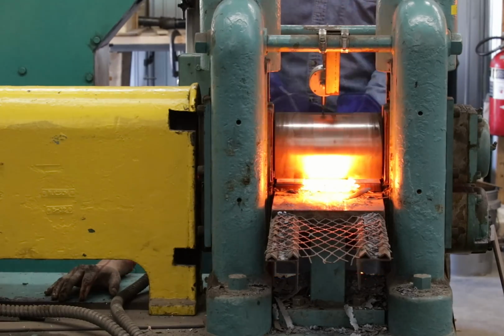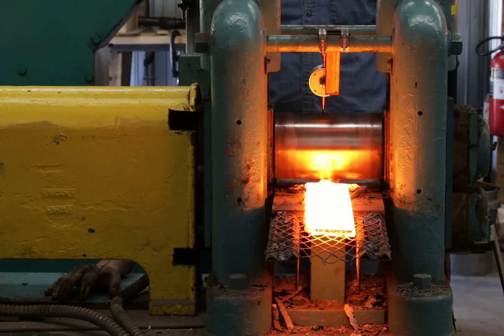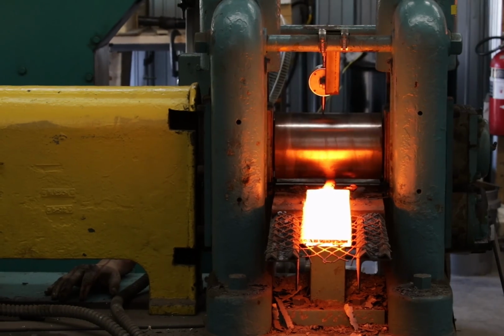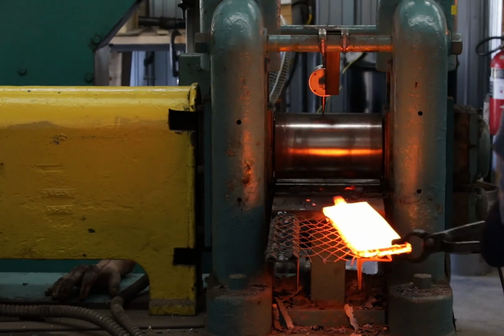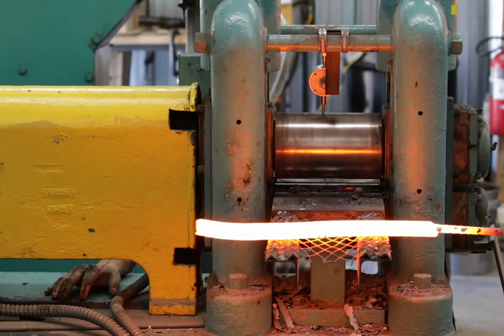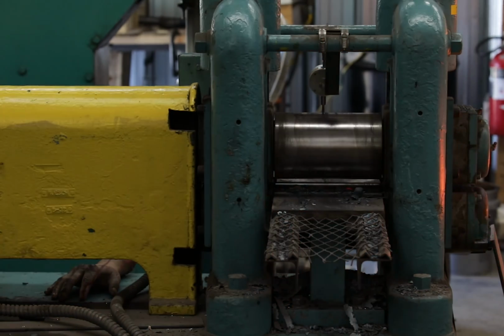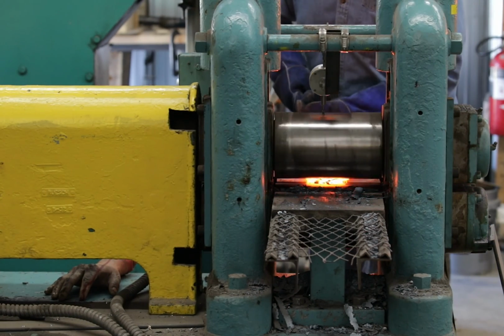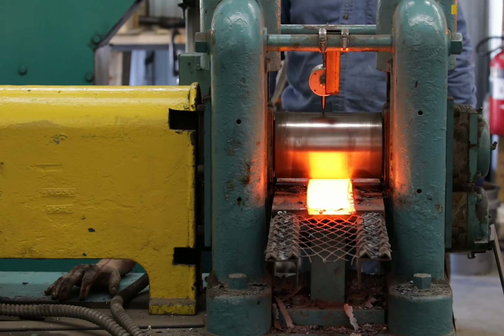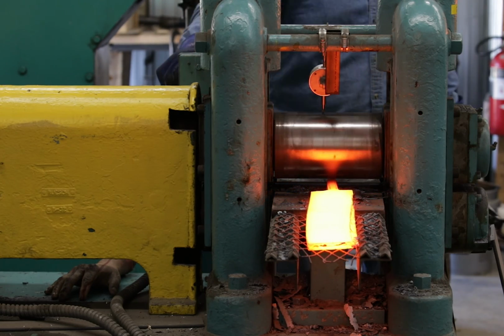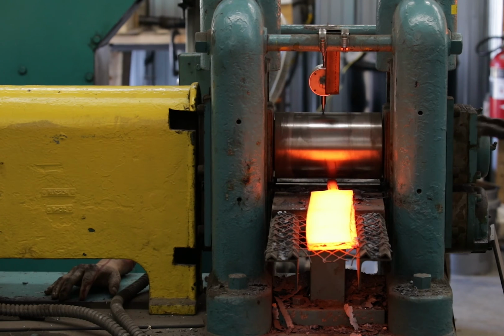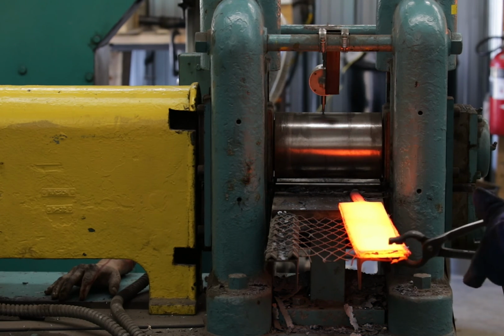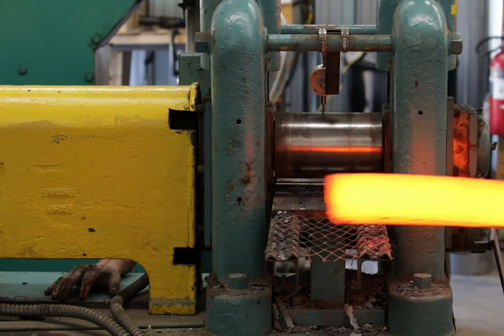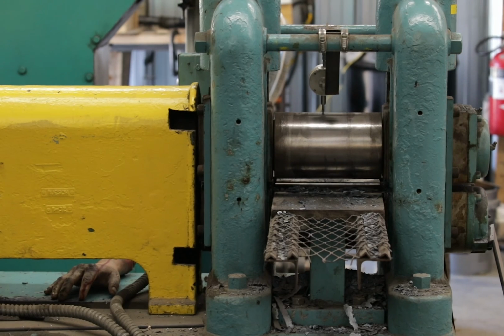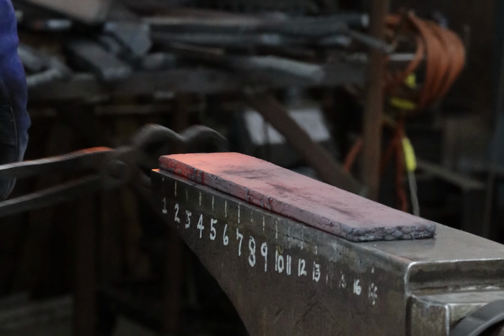Now we've done something interesting here in that my coining press only has room for about a 10-inch billet under the press. And so what we've done is compressed our imagery by 30%. So we've come up with our image like the koi, and then once we have our shape, we'll compress that to 30%. And then we transfer that to our water jet. So both the male and the female portions of this insert weld are actually a compressed image.